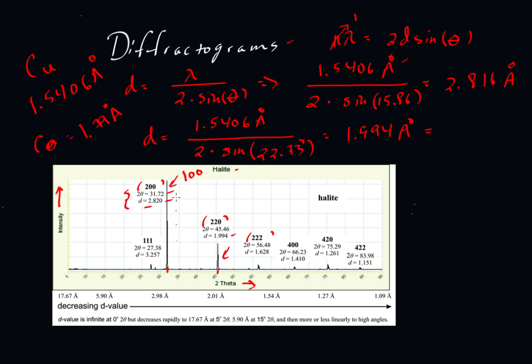So let's just count the boxes here. We have 1, 2, 3, 4, 5, 6 boxes. It goes a little bit beyond 6, but we'll just say this peak has an intensity of 6 units, whatever it is on that intensity scale. And this fellow here has a value of 2. So if this is 100, and it's always going to be 100 for whatever the largest peak is, then this guy here is going to be deemed 2 over 6, which is one-third or 33%, the height of the 100.